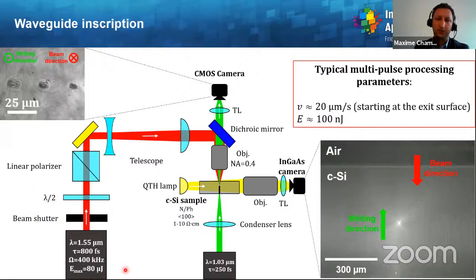So to answer this, experimentally, we have another setup relying on a 1.55 micron wavelength at around 0.8 picosecond duration. Then classically, the beam is focused in the bulk of silicon. We have also one transverse microscope here represented, relying on white light emission and detected with an objective lens, a tube lens, and an InGaAs camera. Besides, we have another microscope here in green for positioning the focus with respect to the entrance surface, as you can see here.